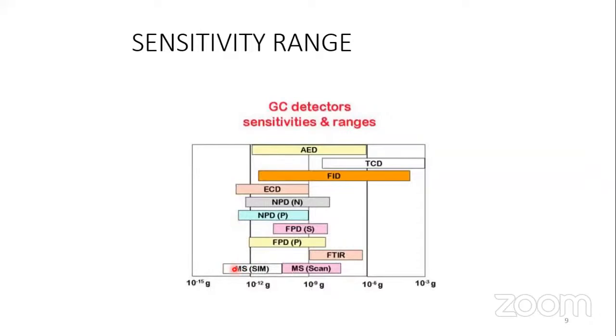Another advantage of MS is that if you consider the electron capture detector, it is only sensitive to halogenated organic compounds. NPD, in phosphorus mode and nitrogen mode, is sensitive to nitrogen and phosphorus containing organic compounds. Same thing is true about FPD. It works in two modes, sulfur and phosphorus. Again, it is sensitive in a particular mode to organic compounds containing sulfur or phosphorus. GC with FTIR is possible, but it has a very, very poor sensitivity. But if you look at MS, it has the highest sensitivity. Now, there are two modes of operation, one is MS scan and MS SIM. We'll learn about these techniques as we move further. Okay, so by this, we know why we require a GCMS and what are the advantages of GCMS in short.